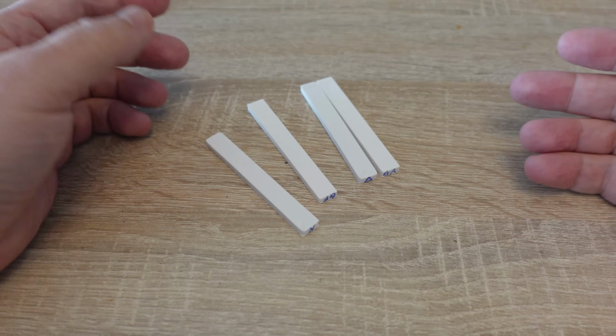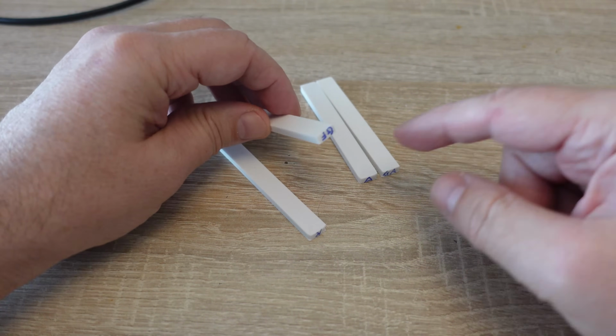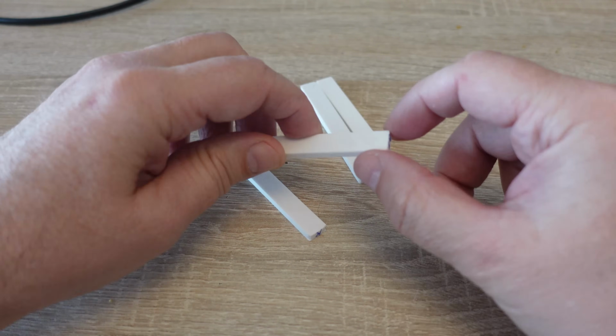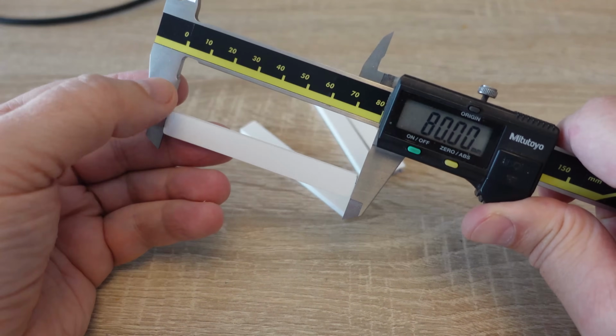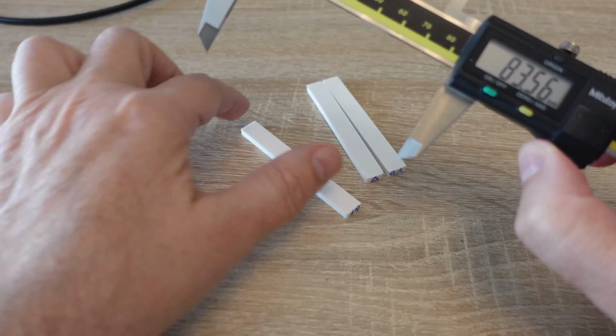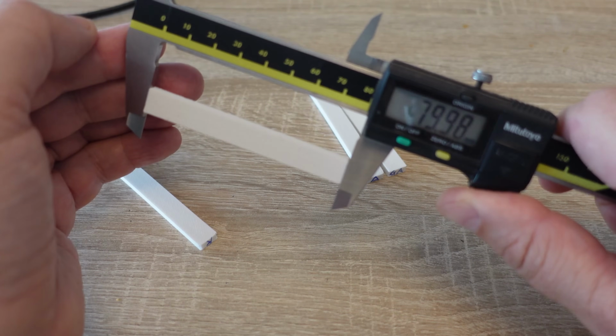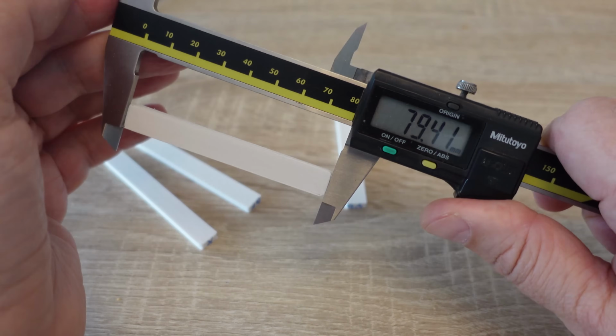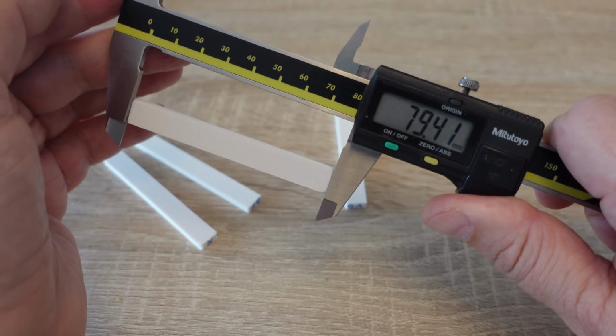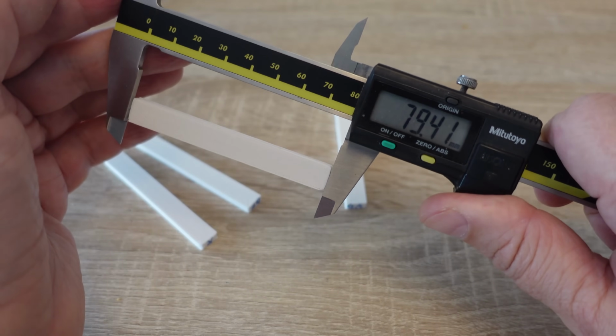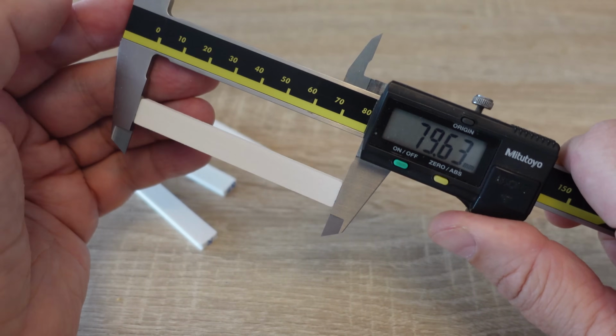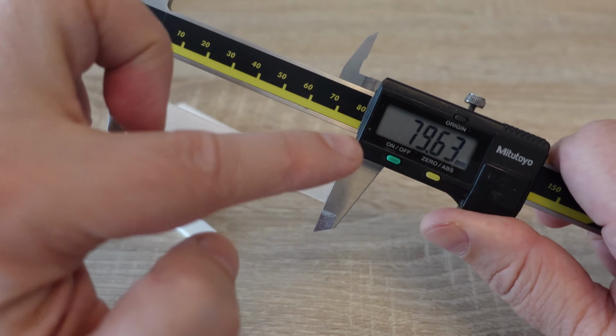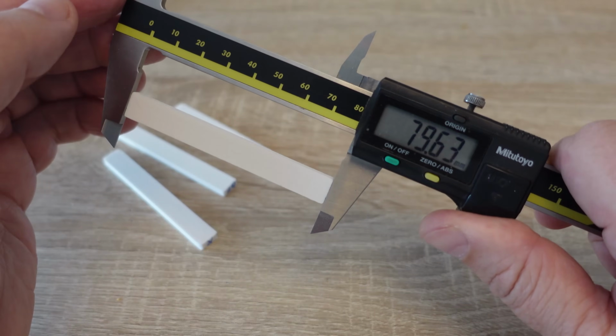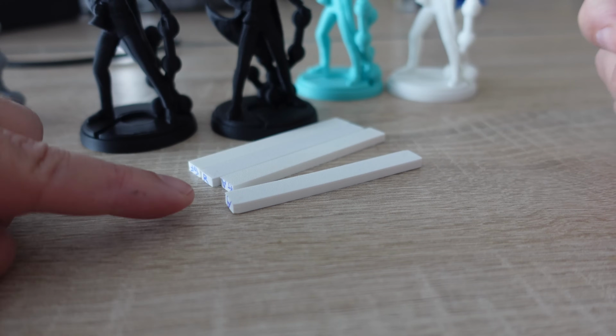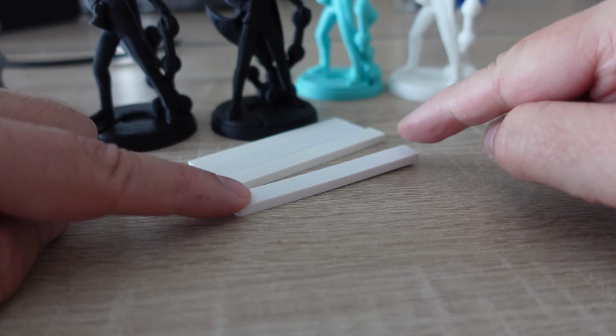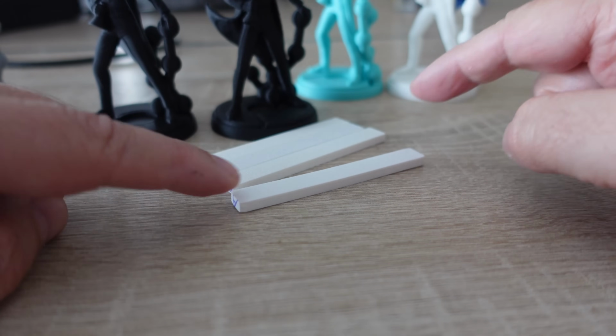Just quickly to check the shrinking, the design length is 80 mm, and I will measure above the elephant foot. This is HT-PLA. This is the glass fiber version. HT-PLA annealed, quite noticeable shrinking, bigger than average ABS. And this is the glass fiber version, and here the shrinking is very similar to regular ABS. And only on annealed HT-PLA I noticed some very minimal warping. Others are straight.